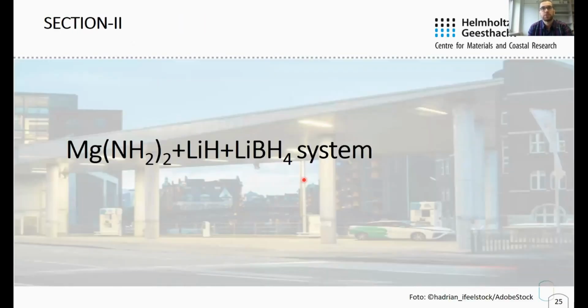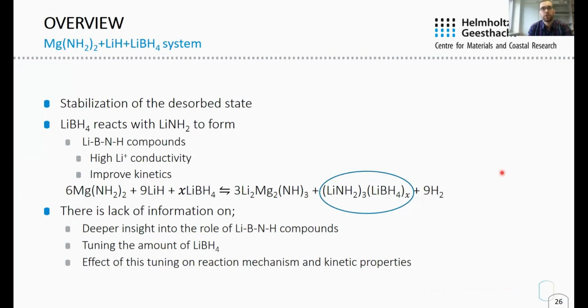The second part of my presentation is devoted to understanding the role of lithium borohydride additive. We know that thermodynamic properties of a system can be altered by stabilizing the desorbed state or destabilizing the absorbed state. Lithium amide is a dehydrogenation product in the magnesium amide lithium hydride system, and the reaction of lithium amide with lithium borohydride forms lithium BNH compounds that have ionic conductivity. These compounds are known to improve the reaction kinetics, but there is a lack of information in understanding the reaction, understanding the role of these compounds.